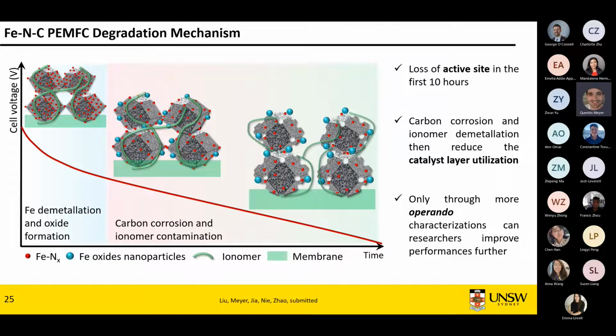Your ionomer also looks thinner, and I made it look like there isn't much contact anymore because you can't conduct. You're creating more heat, have less water, and your ionomer stops functioning as well. So overall, you have this two-step process. First step, you lose active sites. And the second step is you basically reduce the catalyst layer utilization. Your active sites are still present, but it becomes harder and harder to reach them. That's because your catalyst layer is collapsing, because you can't conduct protons. And as a result, your performance will get worse, even though the material, the catalyst you've made, is actually still present.